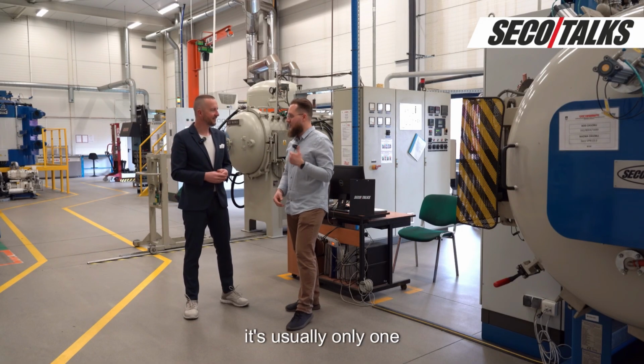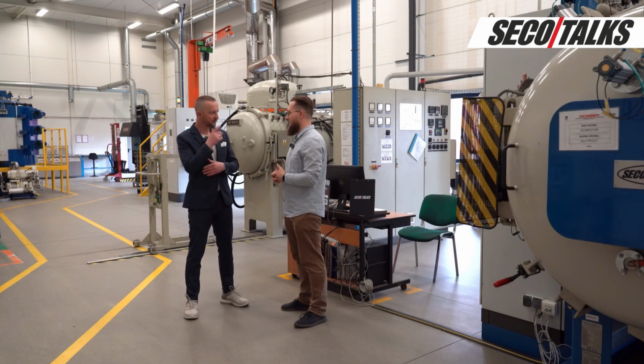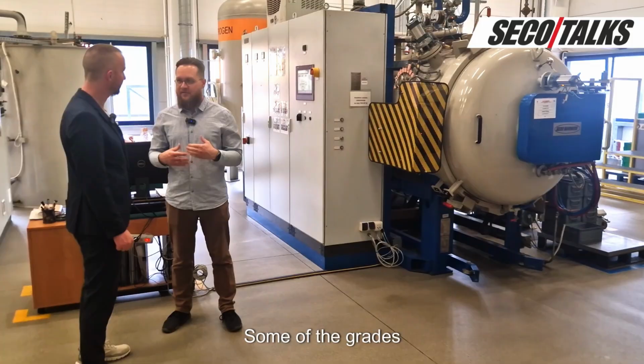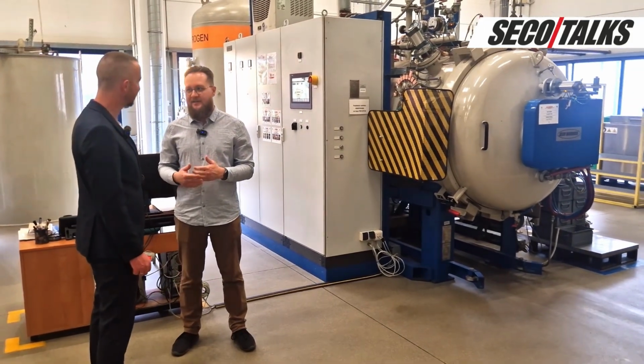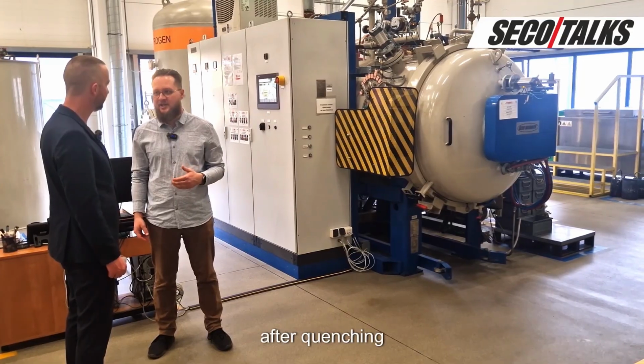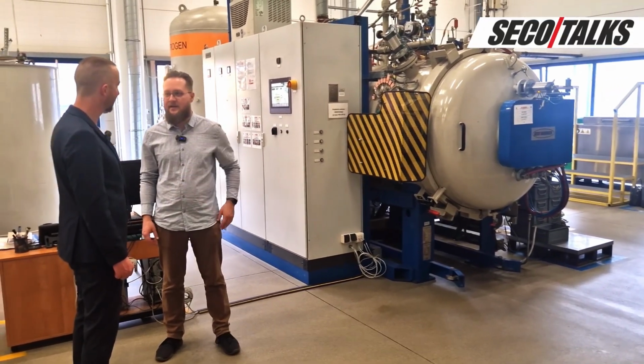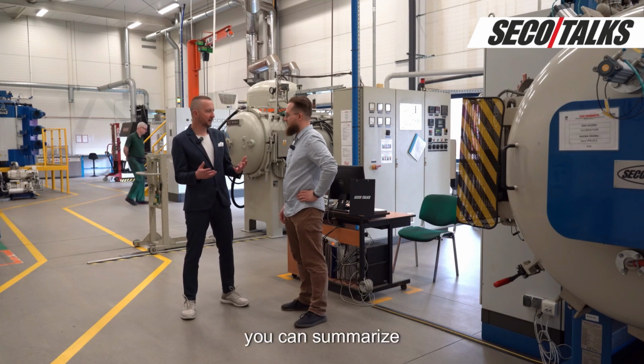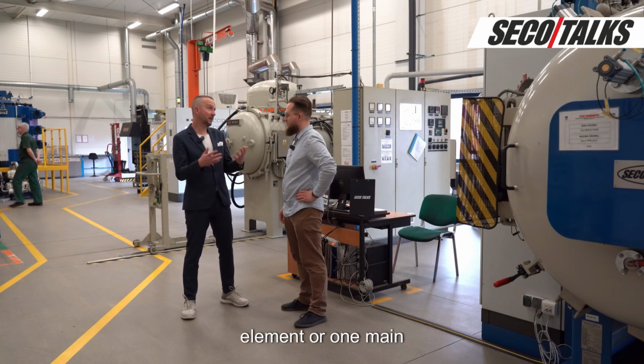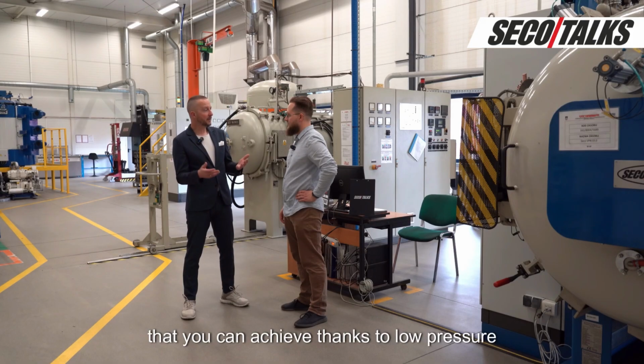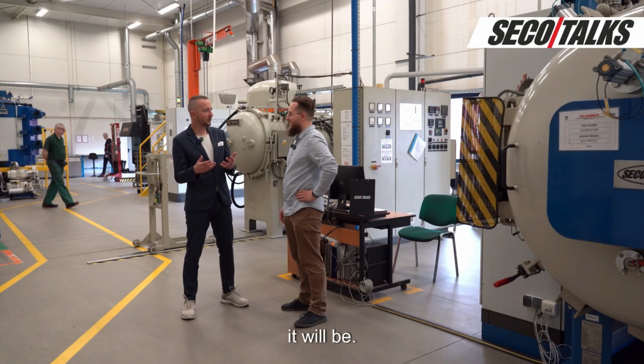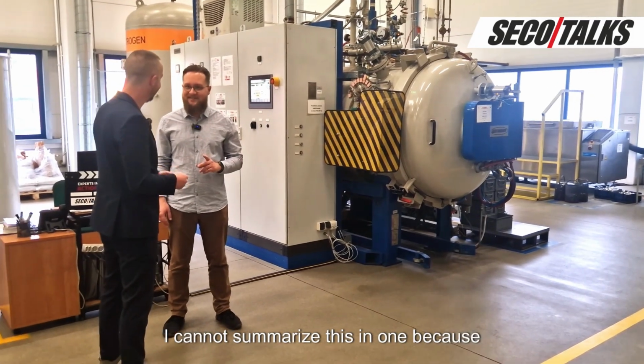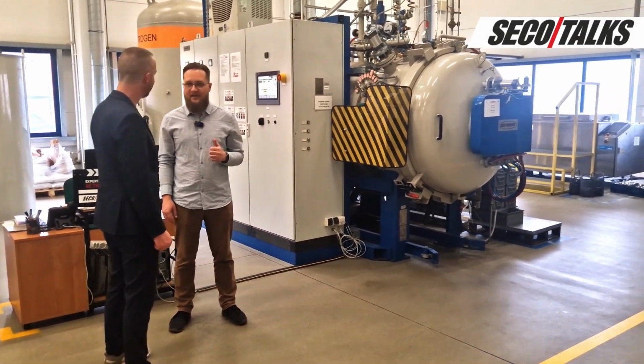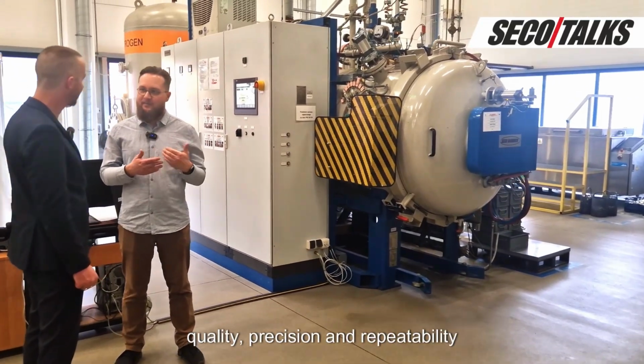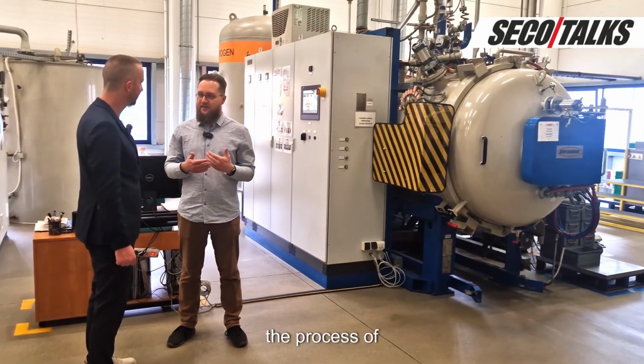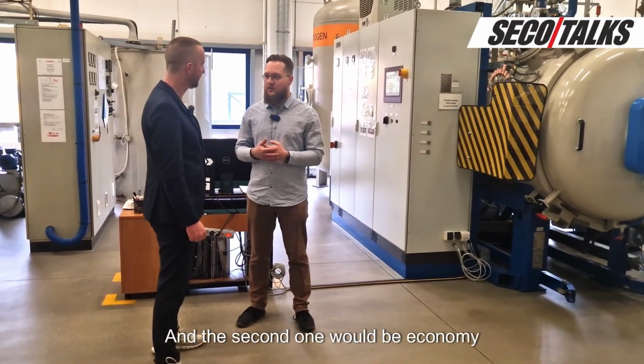Well, it's usually only one process, but this depends on the steel grade that we are carburizing. Some of the grades require sub-zero treatment. So we finish the process after quenching, go to sub-zero, and tempering is in another furnace. Okay, so if you can summarize one main factor that you can achieve thanks to low pressure carburizing, it will be? I cannot summarize this in one because there are two. First will be quality, precision, and repeatability of the process results. And the second one would be economy.